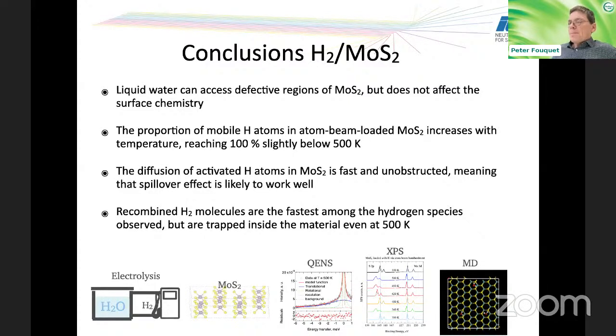So the conclusion of this, and it's nice to have all these different samples and all the different techniques. And I think that's also the richness of the overall remade projects, that you bring these different analytical techniques together, because that provides the essential tool for understanding very complex systems like these. And what we found is that the liquid water actually, as you would expect normally, does not do real chemistry there, but you can access defective regions of the samples, so you have quite strong water uptake, but it doesn't go subsurface.